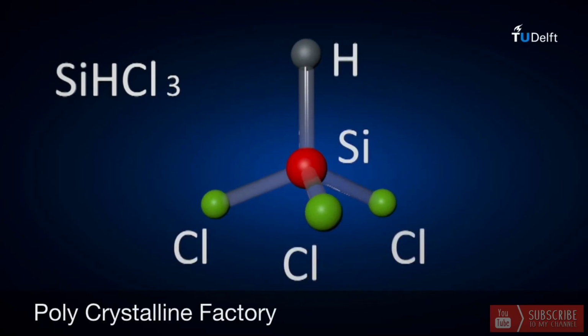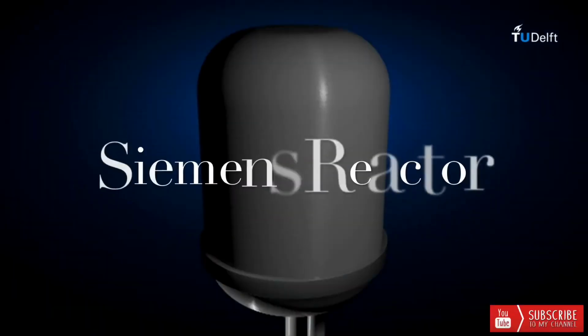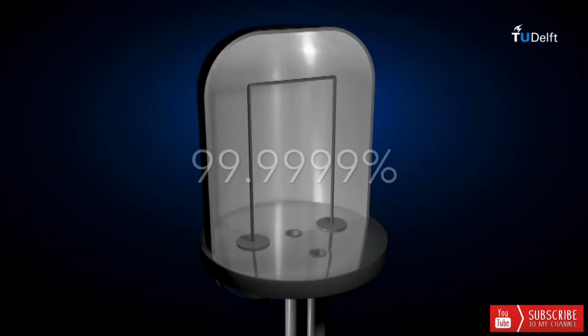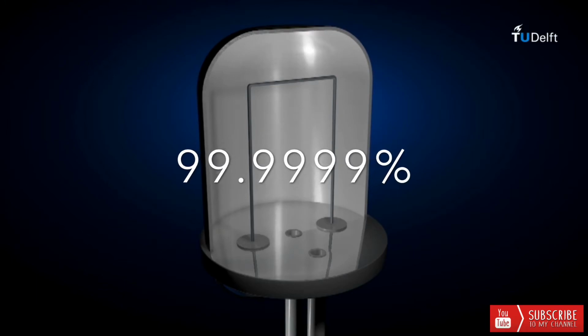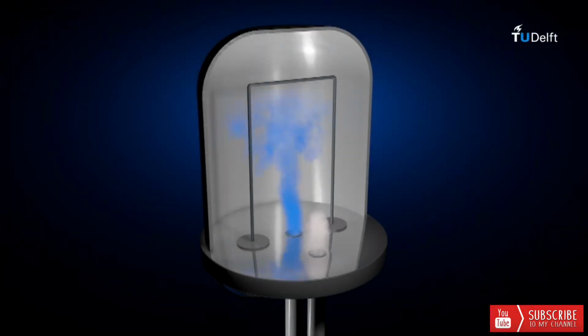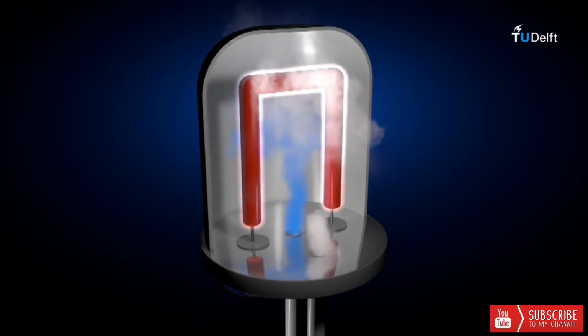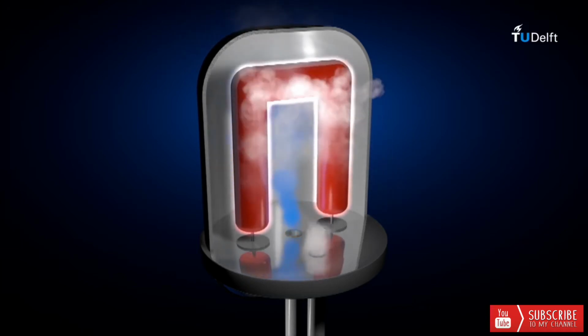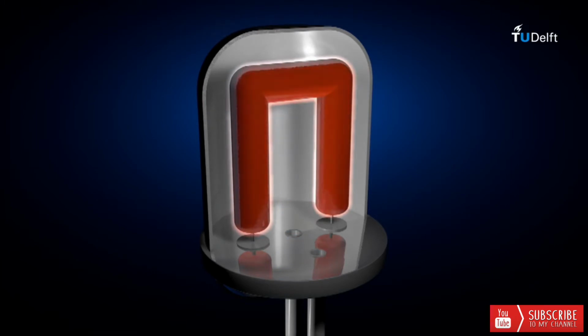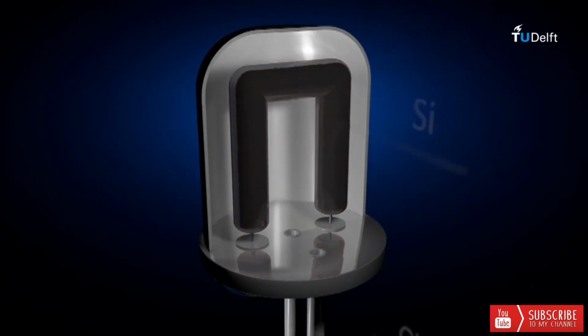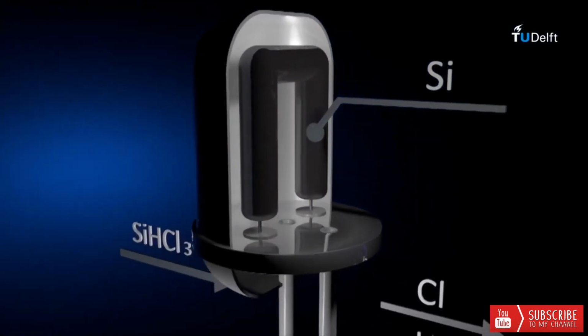In Siemens factory, a hot seed rod of silicon is used to get 99.9999% pure polysilicon. Siemens process is very expensive, but other alternatives like fluidized bed reactors or blowing gas methods cannot generate this much pure silicon out of metallurgical silicon. The next process is making ingots of silicon.